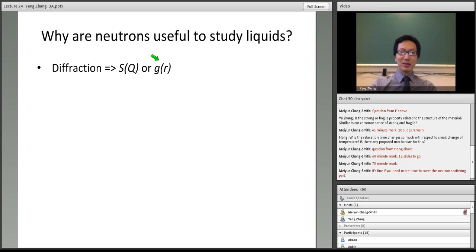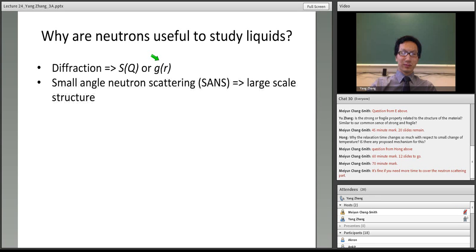Now we know that in the study of supercooled liquids and the glass transition, the structure factor doesn't really change much. If the system is very big, then we can go to very small angles, so-called small angle neutron scattering, that can give us the information of large scale structure. This is very useful to study colloids, polymers, or biomaterials that are relatively large compared to atoms and molecules. We also have neutron reflectometry. With this technique, we can study a liquid interface.